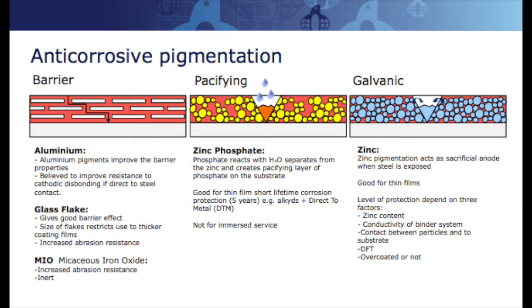The problem is, in real life, zinc phosphates, by nature sensitive to moisture, in a long-term system like an epoxy system, will actually start to help the epoxy system break down. So it starts to have the adverse effect, if you like. It does the opposite of what you want. It will shorten the life of the epoxy coating if you put enough in. So if you're looking at a 25-year system and you put enough zinc phosphate in to actually help you for 25 years, you're putting so much in that once it gets active, it will destroy the coating ultimately.